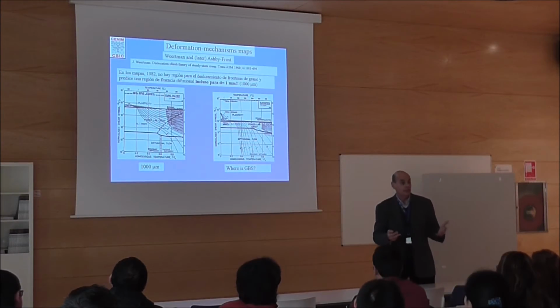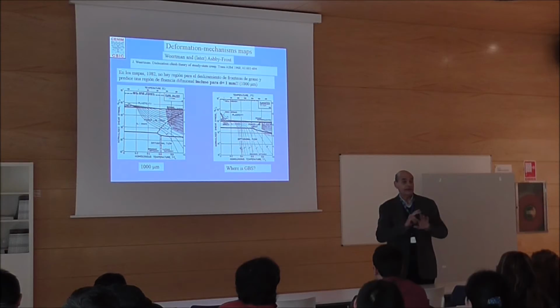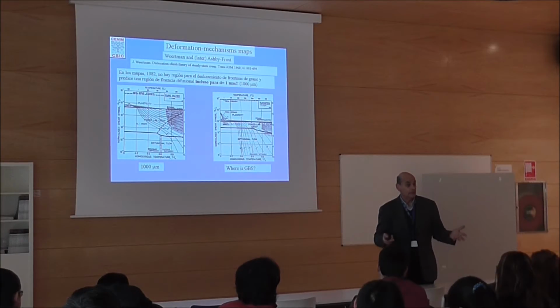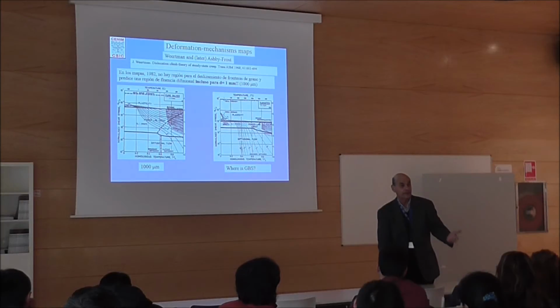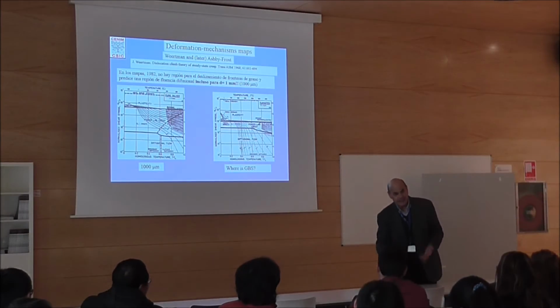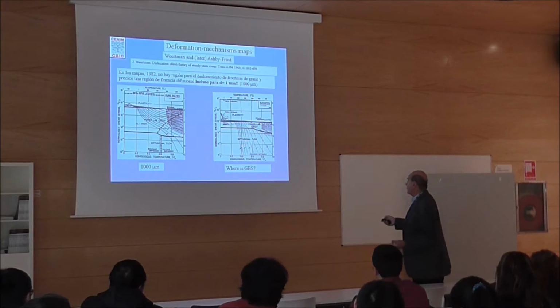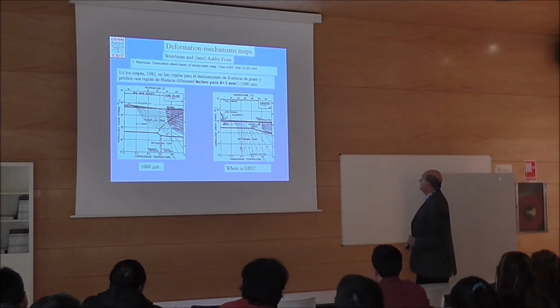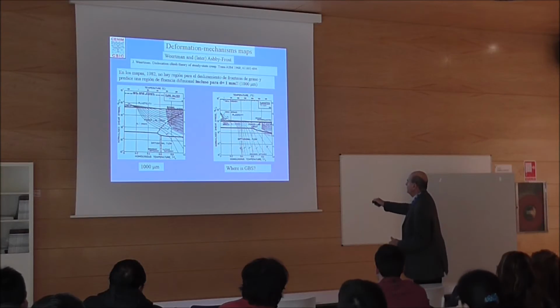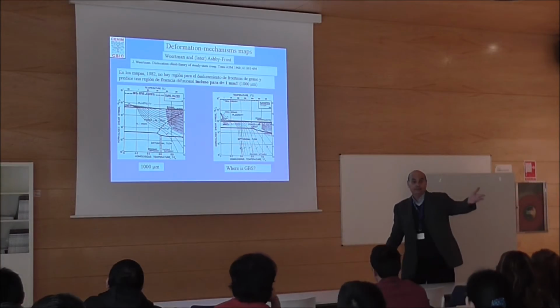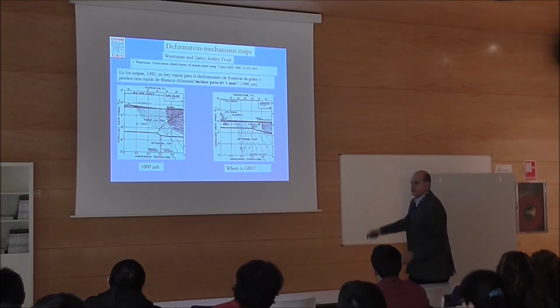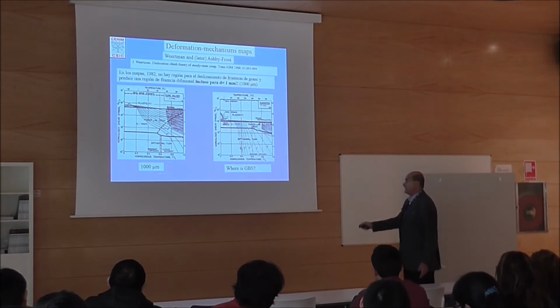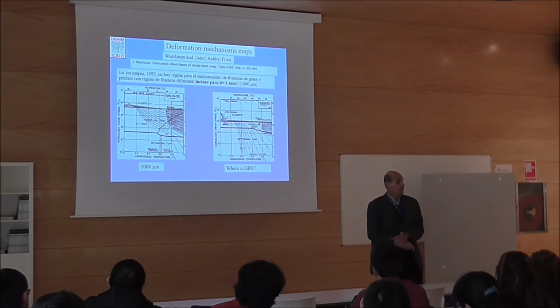And there is a competition between dislocation creep, grain-boundary sliding, and diffusional flow. In this case, they are separated, independent processes. Which one is controlling? The fastest is controlling. If you have an accommodation, the slowest is controlling. And now the fastest is controlling, and of course, diffusional flow is controlling. He mentions all these maps, he has like 200 maps. Diffusional flow. And where is grain-boundary sliding? Well, he never believed in grain-boundary sliding.